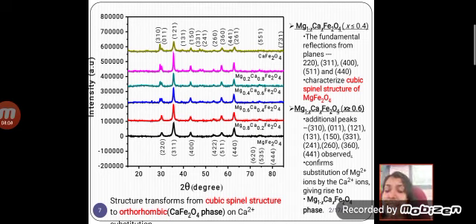And we can see the X-ray diffraction pattern of the magnesium calcium ferrite samples. We can see that the structure transforms from cubic spinel structure to an orthorhombic structure on calcium doping. From the X-ray diffraction pattern, the fundamental reflections from the planes 220, 311, 400, 511 and 440 characterize the cubic spinel structure of magnesium ferrite.